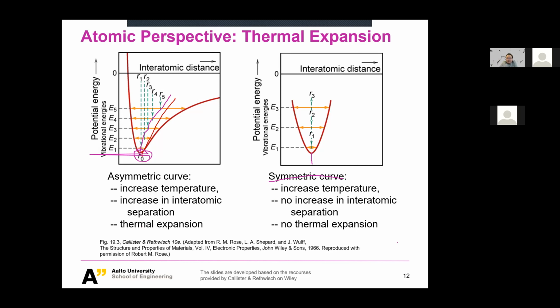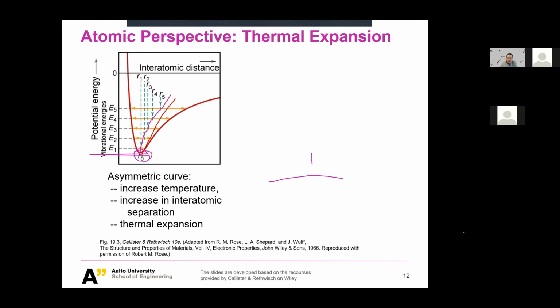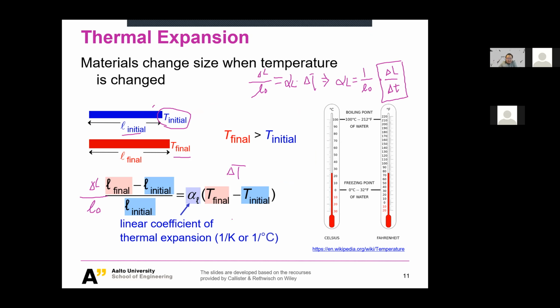And if I could give you one more concept related to thermal expansion: here we're talking about linear thermal expansion. So this is alpha L, where L denotes linear thermal expansion. But in reality, we're not talking about a linear object, except for the thermometer here. When we talk about engineering structures, we're more talking about the volume change, and not just the length change. So in reality, what you see is alpha V, the volume coefficient of thermal expansion. And usually this value is 3 times larger than alpha L.